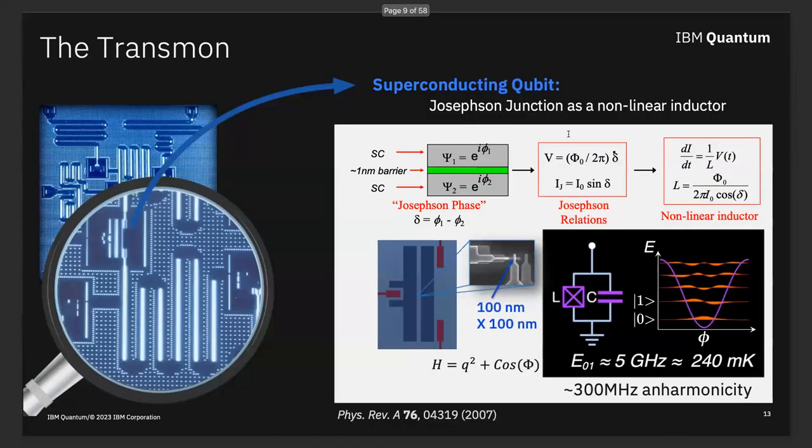The reason comes down to the physical implementation of the qubits. IBM's processors are based on transmon qubits — superconducting capacitors shunted with a Josephson junction. In the limit where the Josephson energy is large compared to the capacitive energy, you can think of it as a nonlinear inductor, giving a very slightly nonlinear LC oscillator — basically a Duffing oscillator. That anharmonicity lets you use it as a qubit. Our quantum states are microwave photons inside these LC oscillators. Anything with any microwave loss tangent will cause our qubits to decay. We typically get T1s of a couple hundred microseconds.